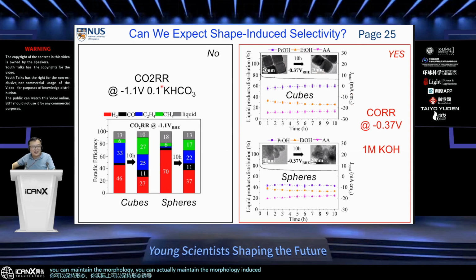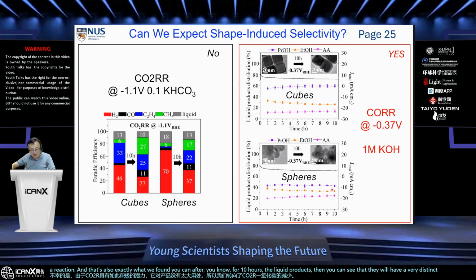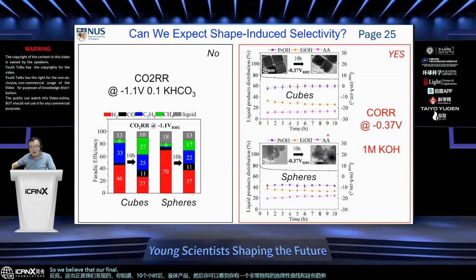Unfortunately, for the CO2R, at such a positive potential, it doesn't make too much useful product. So we turn to the COR, carbon monoxide reduction reaction, and that's also exactly what we found. After 10 hours, those are the liquid products. Then you can see that they have a very distinctive selectivity profile, and those trends are relatively stable compared to the CO2R case. So we believe that our finding is true, because of those experiments.